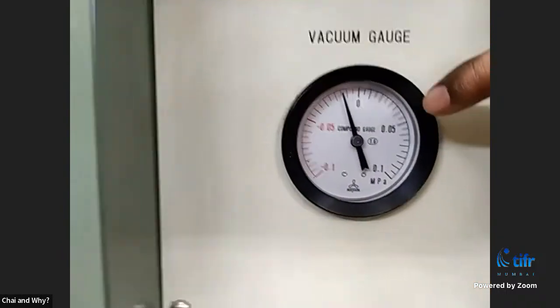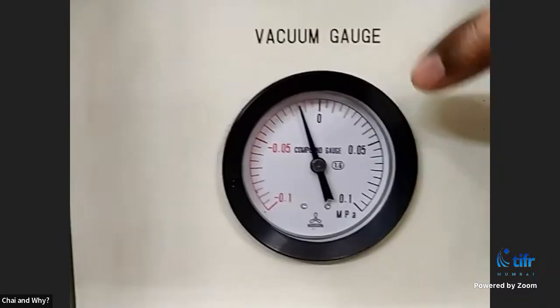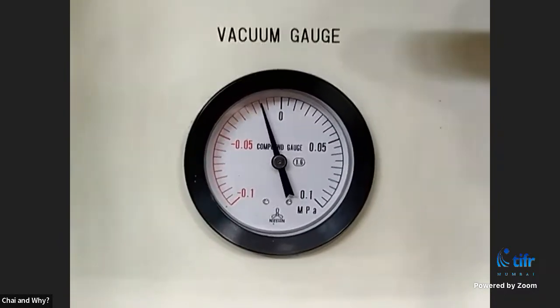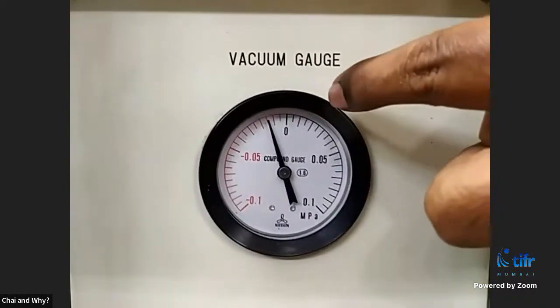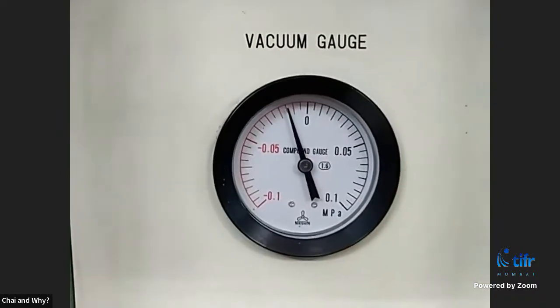Right now you can show that this is the chamber pressure as of now. It is filled with argon gas, under a partial pressure of argon gas. The reason for this partial pressure is that if you put it at atmospheric pressure or a little excess atmospheric pressure, when we heat up these metals, gases come out of these metals. Also the argon inside gets expanded. So to avoid the excess pressure, we are using a little bit of partial pressure of argon gas.